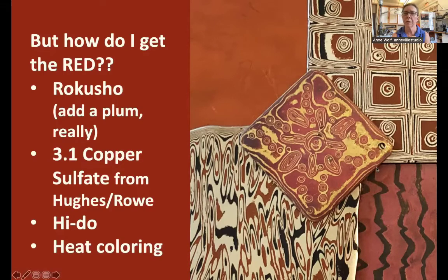There's a hole here because that made it easy. I just strung it on a steel wire and used a torch. Usually you do the back side, the other side will get better color because it has more reduction. And then when it is almost melting, just before the copper melts, plunge it in water. A little tip, make the water quite warm, almost steaming, and dissolve about a teaspoon of borax in your water container. The cool thing about that is that it will actually fume a little sealant on to your piece. So it makes a really nice hard coating and it's quite durable. The borax does not affect the color, but it helps seal the patina.